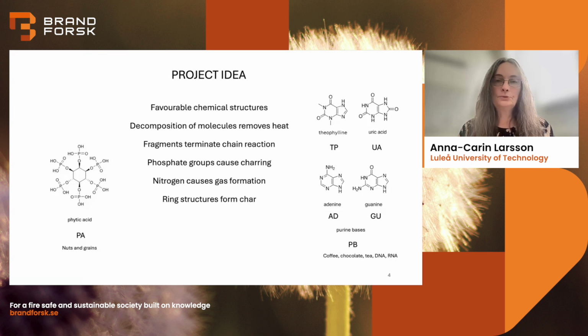Phosphate groups are known to cause charring, which prevents the emission of pyrolysis gases. Species containing nitrogen are known to cause gas formation, which can dilute and quench the pyrolysis. Molecules with ring structures can form a char that insulates the underlying material.